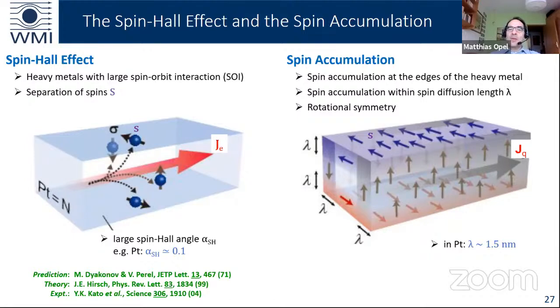So we have the magnetically ordered material and we have the platinum electrode. Both have thicknesses. So with regard to the platinum electrode, we find that the maximum effect we see at a platinum thickness of 3 nanometers. And we think the reason is the spin diffusion length in platinum. This is around 1.5 nanometers. 3 nanometers would then mean that the spin left go to the top and the spin right to the bottom, as I told you. And then we have a more or less perfect spin separation if we have twice the spin diffusion length. So maximum is at 3 nanometers of platinum.